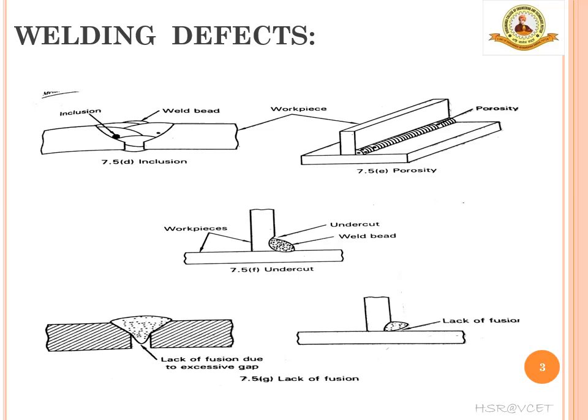The last defect is lack of fusion, sometimes also called overlapping. Lack of fusion is a failure of the welding process to fuse together the layers of the base metal — the weld metal just goes over the workpiece surface. Common causes are low welding currents, excessive surface impurities on the workpiece, improper electrode type or size, wrong polarity, and stray arc.